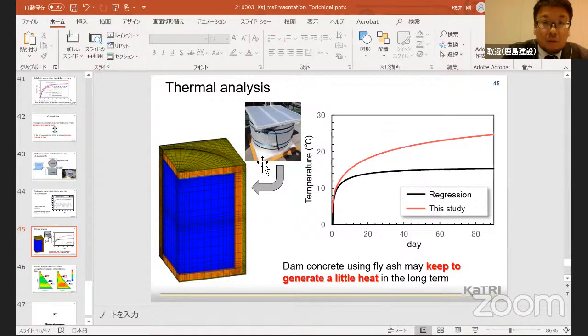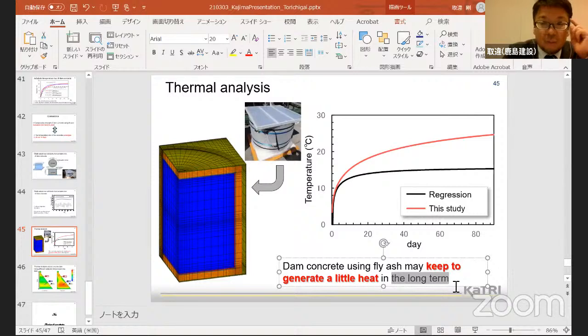And we tried to simulate some analysis to get the real adiabatic temperature rise. It seems to be this line like that. So concrete using fly ash may keep generating a little bit of heat in the long term, we think.